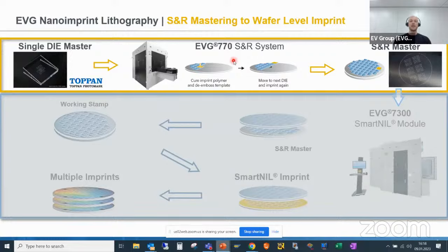This template will then be used for imprinting the single die, which you can see here in the master, several times on a new carrier wafer. This will be repeated until we have a fully populated step and repeat polymer master template in the end. The purpose of this is to create a cheap process and to not have the risk of damaging the original master while processing, for example.